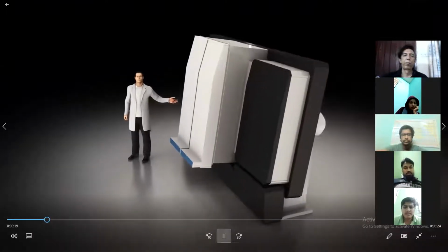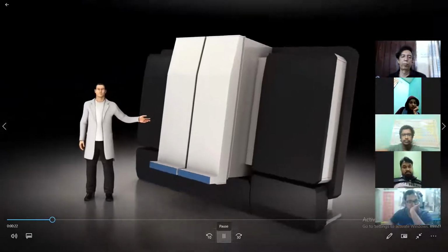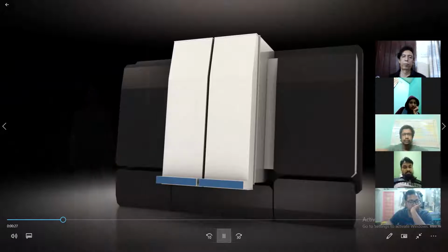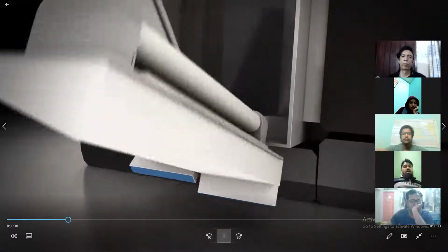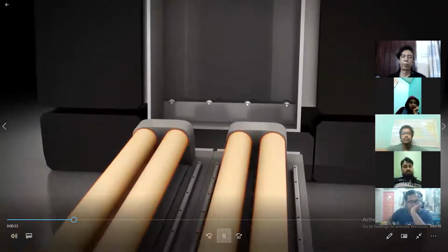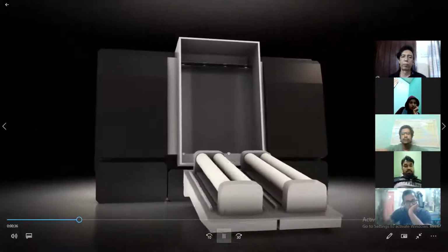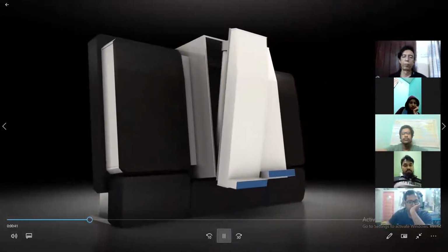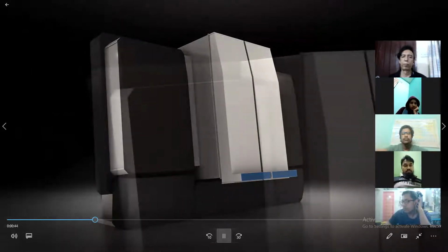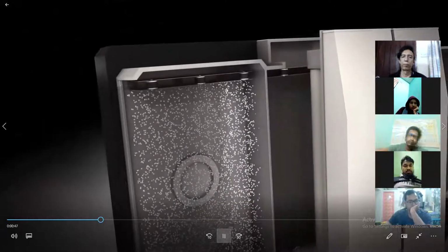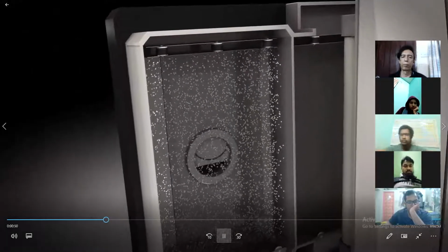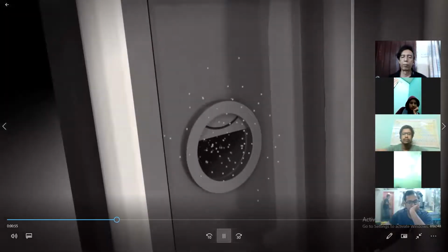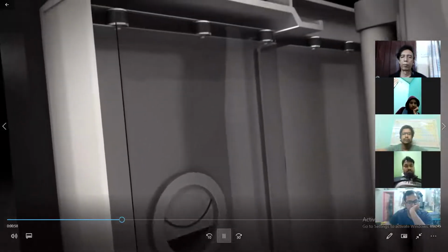Sputtering deposition is done in a vacuum chamber. The most common substrate for the thin layers is glass. The sputter system can have different sizes depending on the application. The source of the thin film material is a planar or rotary sputtering target of metal, ceramic, or even plastic. Molybdenum targets, for example, are used to produce conductive thin films in displays or thin film solar cells. At this point, the process starts. Air is continuously removed by vacuum pumps. The base pressure in the vacuum is around 10 to the -6 millibar, which equals about a billionth of the atmospheric pressure.